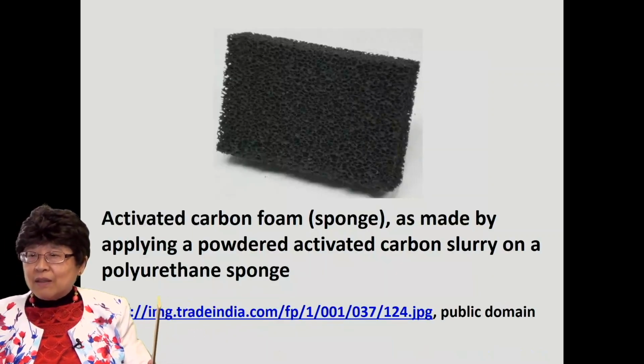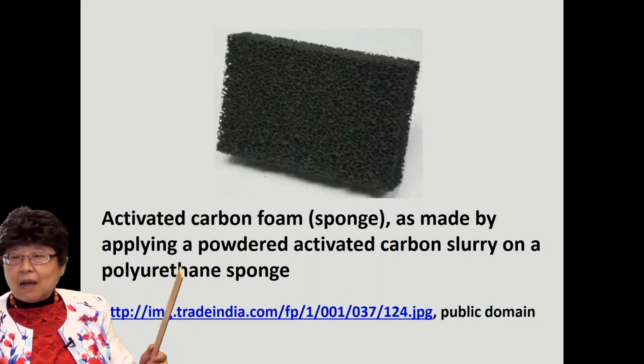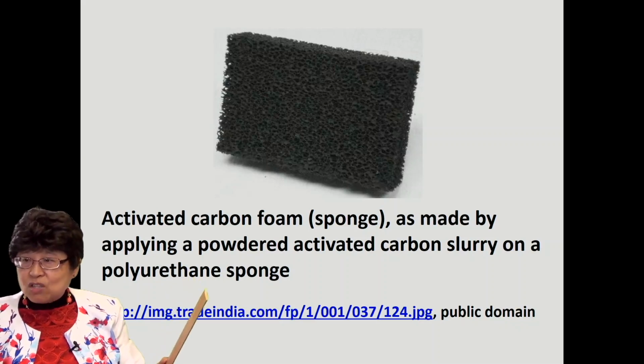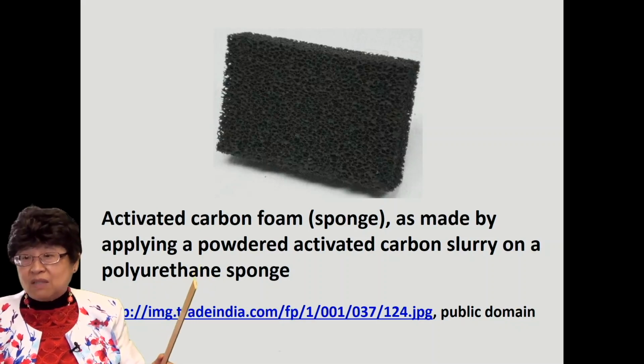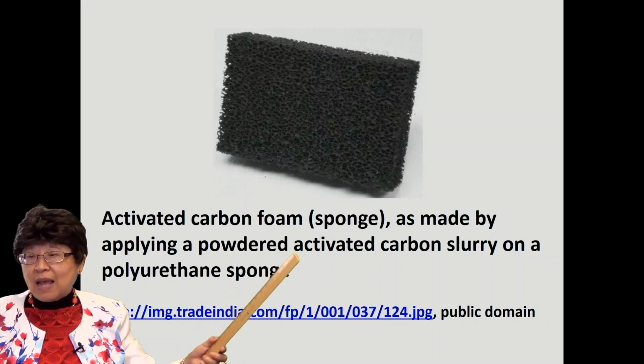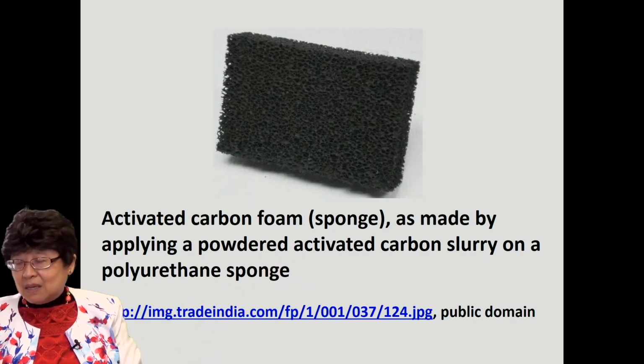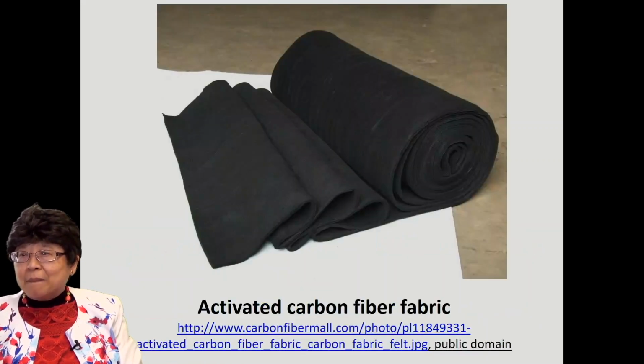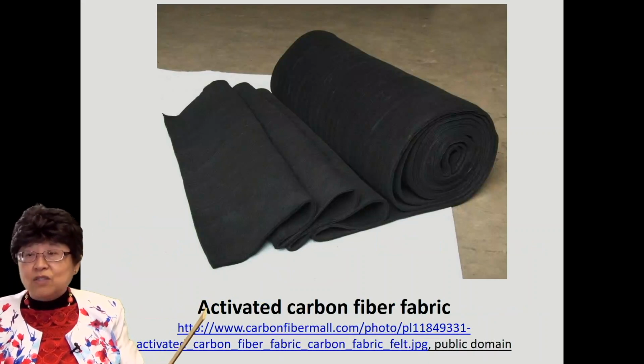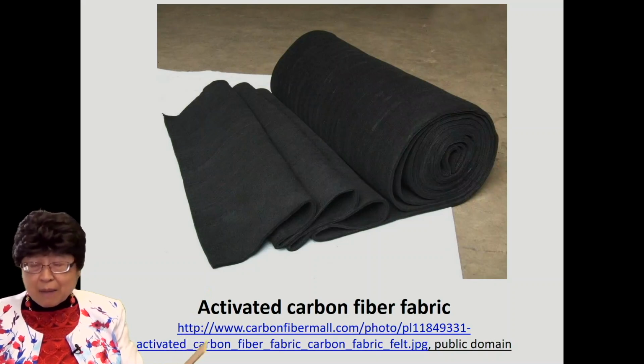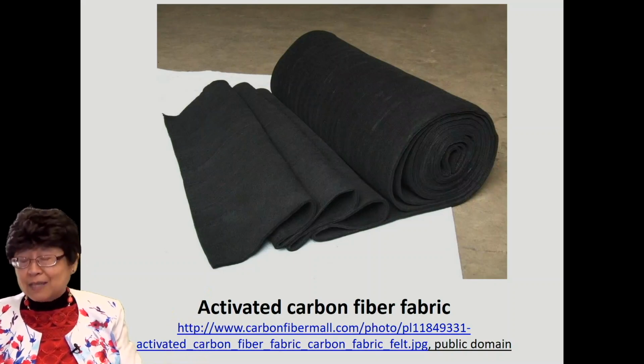And this is another form, which is a polyurethane sponge, which has been coated with powdered activated carbon slurry. And here's yet another form, which is activated carbon fiber cloth. That is, you activate the carbon fiber and make a cloth out of it.